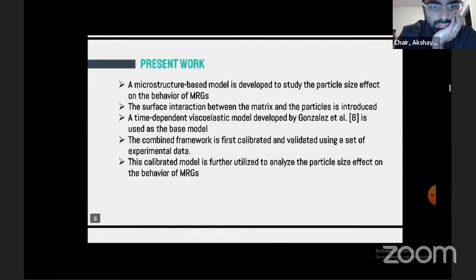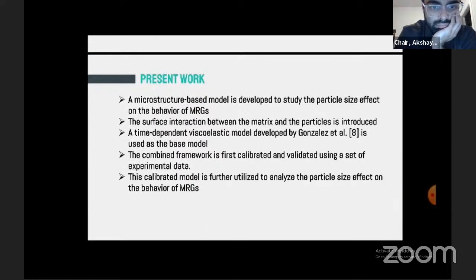So in the present work, we start off with a microstructure-based model developed to study the particle size effect, and the surface interaction between the matrix and the particles will be introduced. A time-dependent viscoelastic model which has already been developed will be used as a base model. The combined framework will be calibrated and validated using a set of experimental data. This calibrated model will be further used to analyze the particle size effect on the behavior of the MR gels.